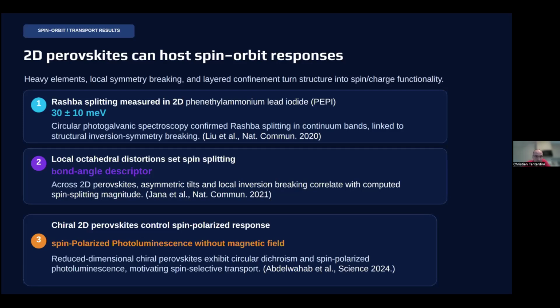Another aspect of 2D perovskites that can be very interesting to study is the presence of a heavy element. Of course, now we are in a world where we are moving from lead perovskites to non-lead perovskites because we want a more environmentally green world. But there are also other heavy elements that can be used successfully, and we can have different effects. For example, we can have a Rashba splitting, which is easily measured, and we can also have chiral 2D perovskites with spin-polarized photoluminescence without a magnetic field. This is very interesting because we can tune the photoluminescence without the counter effect of the magnetic field.